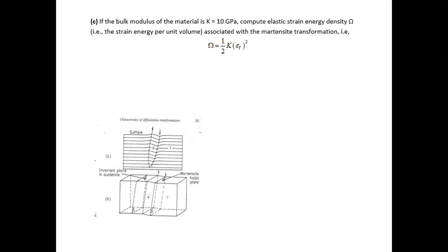When you do the transformation, you don't just insert one solid into the other, but you shear the system to create a kind of sheared band of structure, and this will allow you to accommodate the actual change of volume, but not increase too much of the strain energy. Okay, I'll stop at this level because I think you're probably going to see this in more detail in the physical metallurgy class. But for now, this is the highest level I'm going to mention.